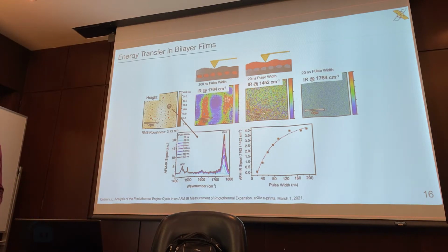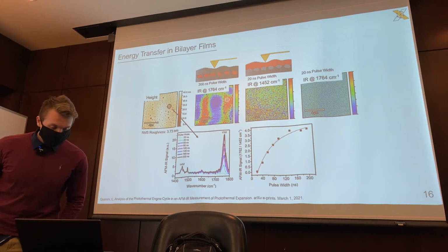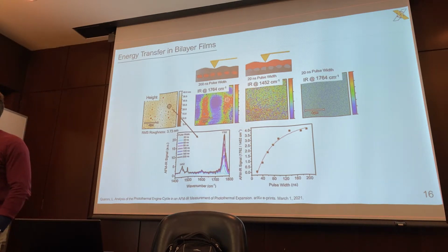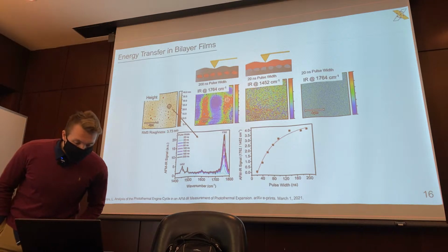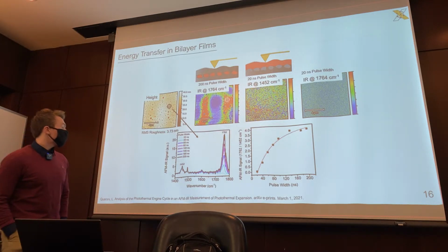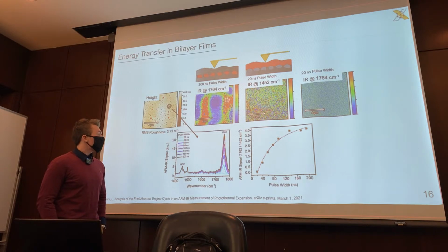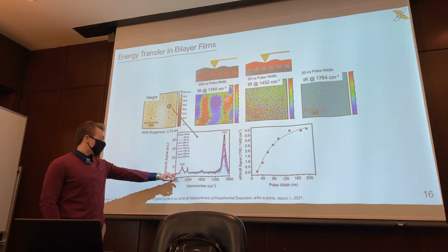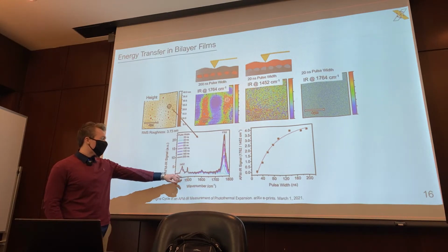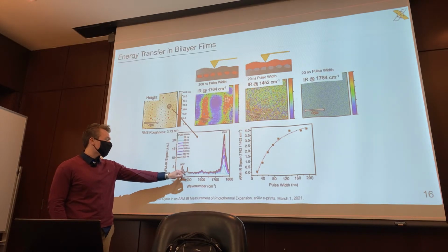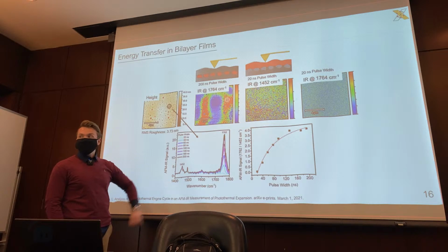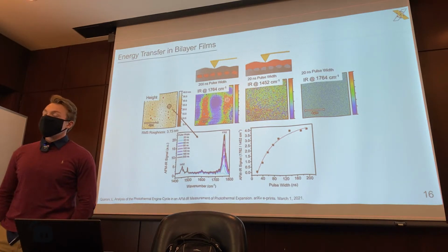For the absorption peak at 1452, do you only have a signal for the longer times, or do you have all of them but they all overlap? Whether I'm seeing overlap at 1452? Yeah, for the 1452, I can only see the dark blue, but I'm not sure for the light blue, like 20 or 40 nanoseconds. Do you observe any absorption peak? The cyan color doesn't really show up on this white very well, but they're all normalized at 1452. So they all show this exact same absorption pattern here. All the pulse widths show the signal, but they overlap.